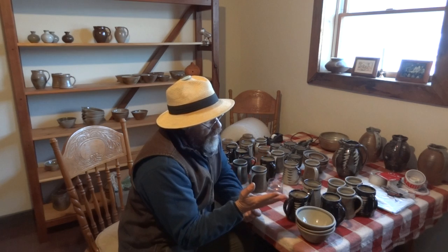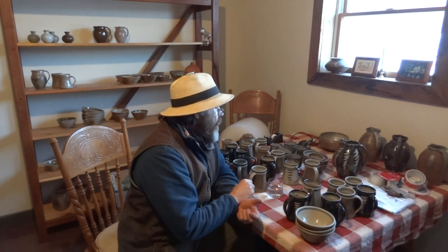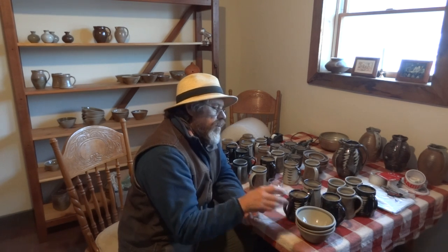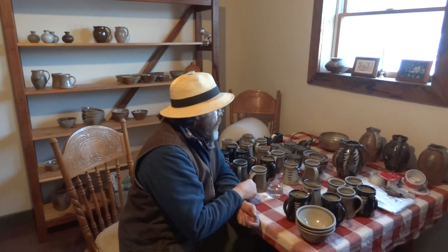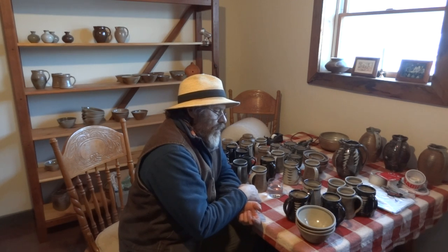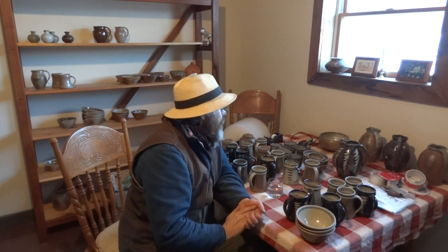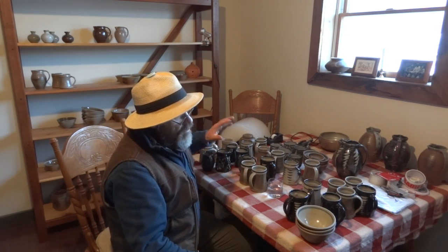As a result of going more into oxidization, the temperature rocketed up rather fast. And that's another cause of bloating, can be over-firing, going too fast. And I think that was actually the real cause of this. All of these ones that are really badly bloated, and others that are out there in the kiln shed, are all on the bottom shelf where the kiln was rather hot, and where it was oxidized, and that's where it got overfired. The shelves above that were better, were okay, really. They weren't the best, but the kiln was in general oxidized and bloated.